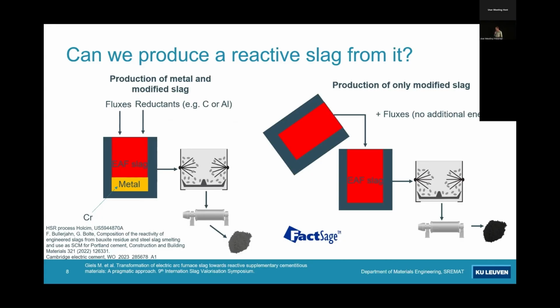So we were looking into a more economical solution by, when they're pouring the slag out of the EAF, basically putting additions to it, fluxes, so minor fluxes, that lower the liquidus temperature while actually keeping the slag molten. So the melt temperature is dropping, but the liquidus temperature is dropping faster. So actually the material stays in a melt, in theory. And then you create this material, which can be an upgraded SCM.